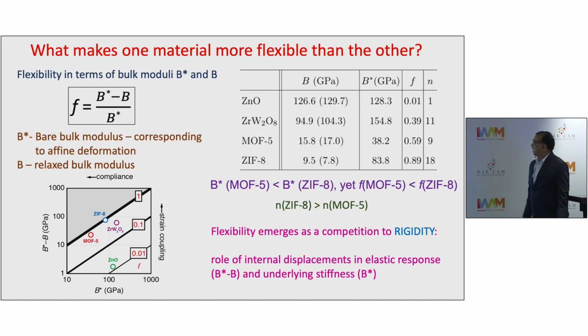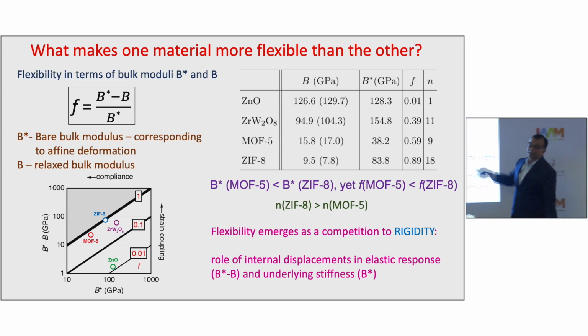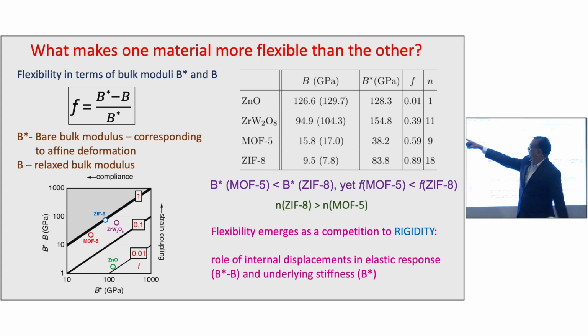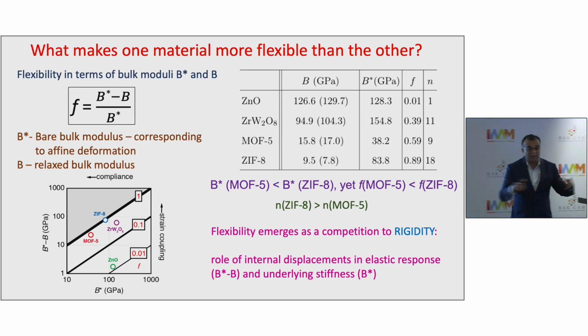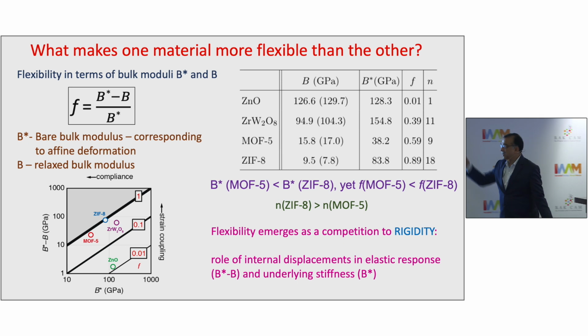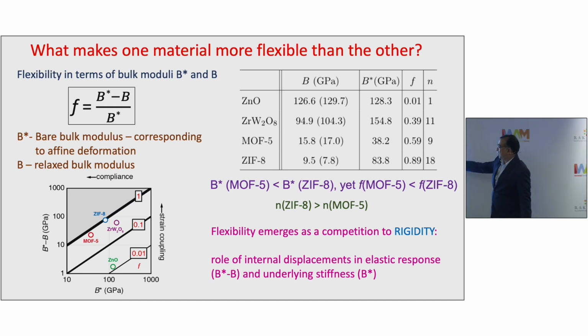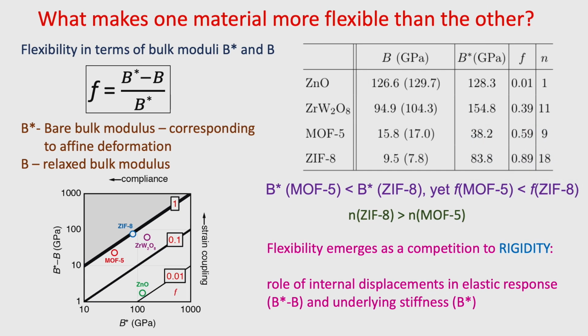And here is the expression of flexibility written in terms of bulk moduli, where the bottom is the bulk modulus corresponding to infinitely fast or affine deformation, and the numerator is the reduction in that by relaxation. You will see that in MOF5 the elastic cost is actually lower than the elastic energy cost of ZIF8. But what changes is this n, which gives you the number of internal degrees of freedom which are relaxing to give you a lower energy state for a given strain. And that's where ZIF8 wins. It has many more ways of adjusting internally and lowering its energy, and hence it is more flexible than MOF5.